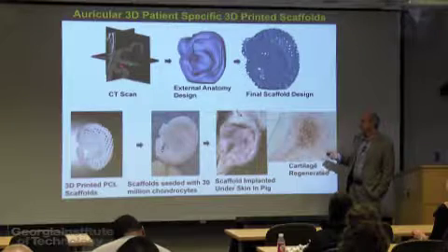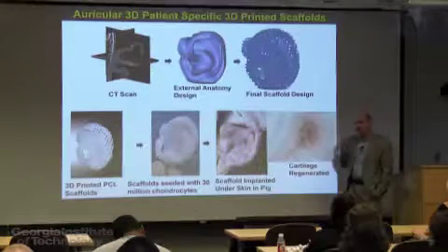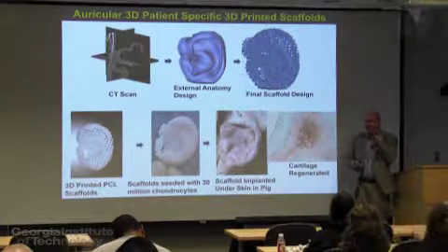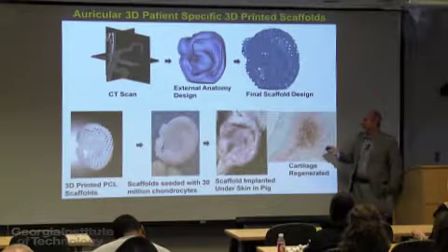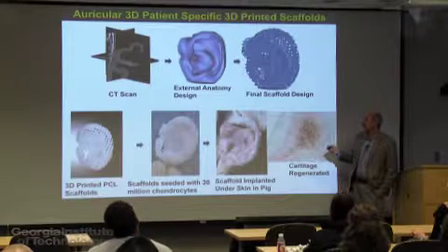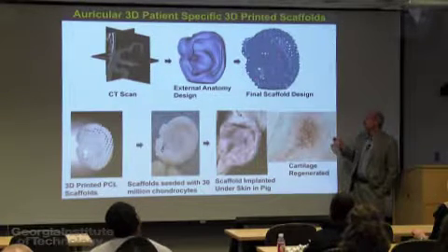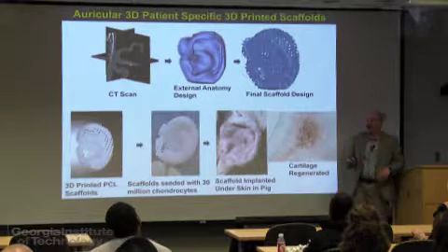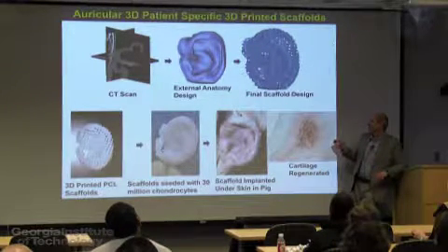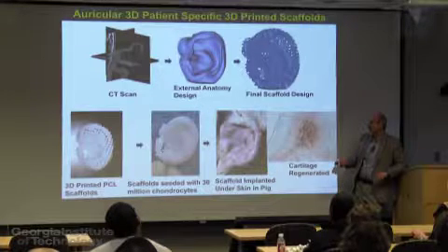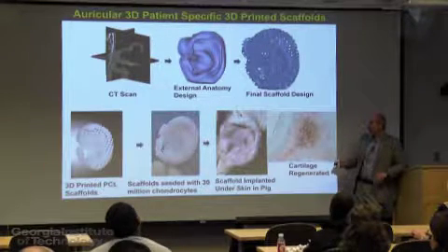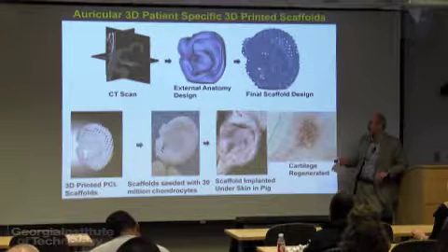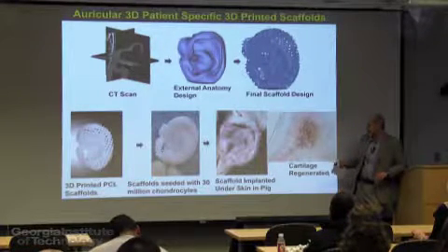So in this case with microtia, which generally is unilateral, affects only one side, you can actually take a mirror image of the good ear, generate the anatomic structure of that, design a porous structure from which you can deliver the biologics, create a porous anatomic design, 3D print that, and then in this case, we're using a hydrogel with about 30 million chondrocytes to seed the device.